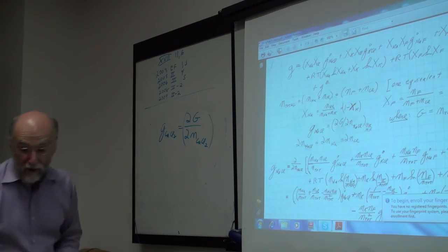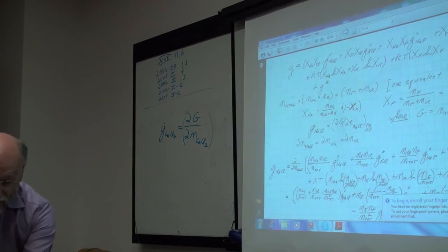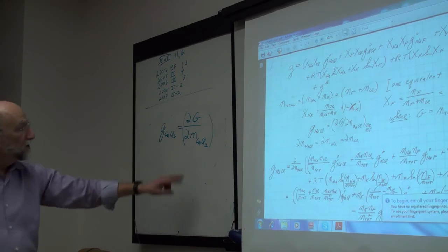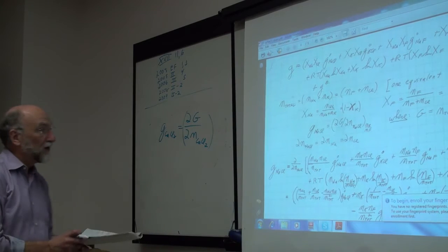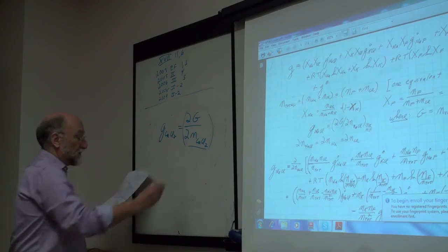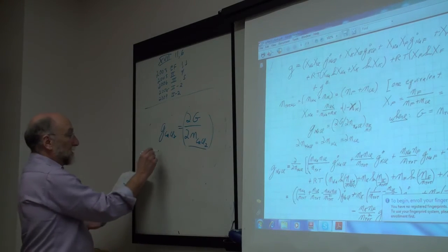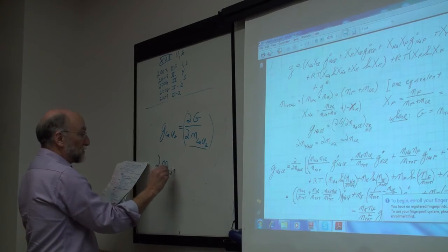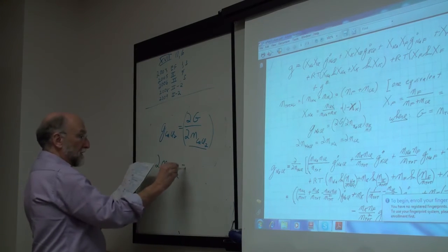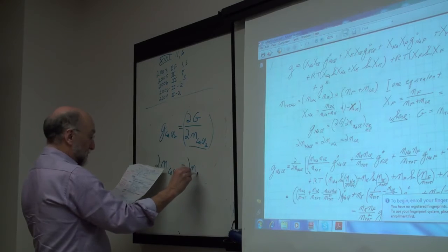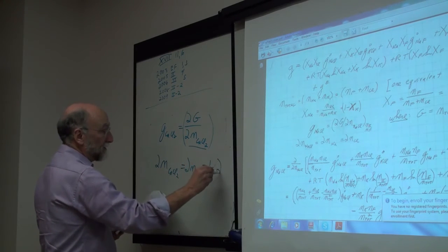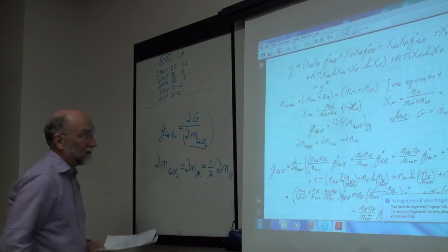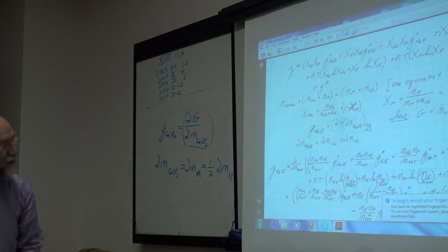Now what you have to notice is that when you're trying to get the chemical potential of calcium chloride, as you're adding calcium chloride, the number of moles of calcium chloride which you add is equal to the number of moles of calcium, but that's equal to 1/2 the number of chlorine.